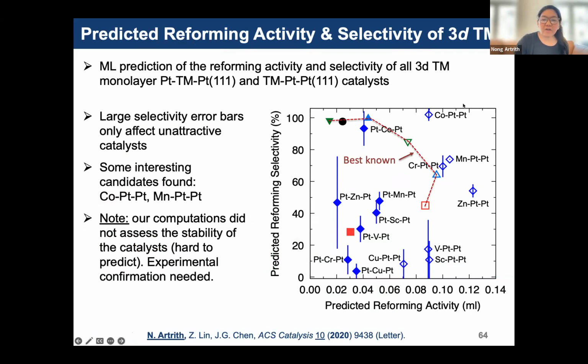But what we see here is we got a few more candidates that could also be good. So why don't the experimental collaborators see this? Because of one parameter that we don't include, which is the stability of the catalysts, because it's also hard to predict in this case, and experimental collaborators also don't offer this. But anyway, even with this type of feature that we use, it can already give us some idea that we can also get a good catalyst for ethanol reforming and predict activity and selectivities, and even propose new types of materials.